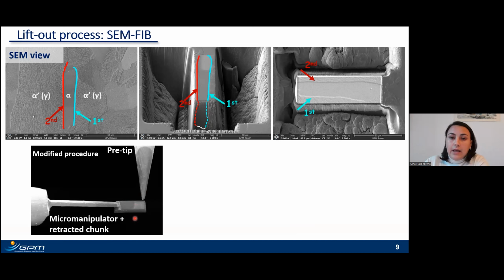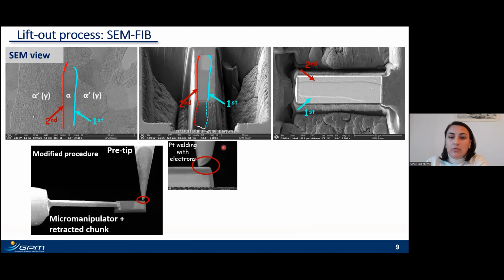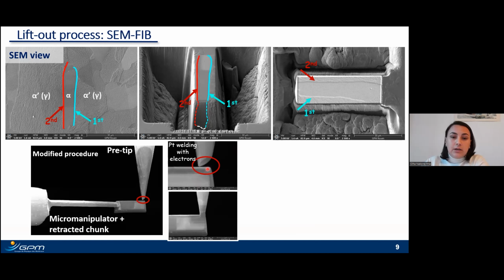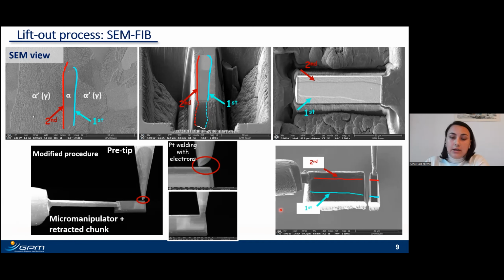It was a bit challenging part of the sample preparation because of the shadowing effect by FIB welding here. So first, we did some welding by SEM using the electrons, and then if necessary, we changed the configuration and added welding using FIB. It is a bit tricky, but as a result, we can obtain a piece of material on the pre-tip that contains both interfaces as we wanted.